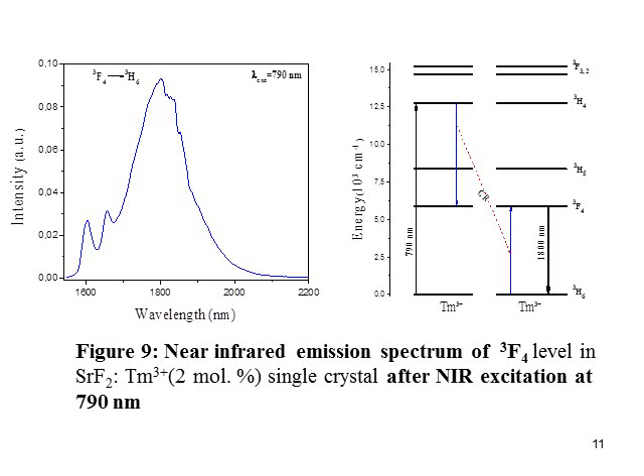We are also able to record the infrared emission around 1.8 micrometer, which is known to have many practical uses. The emission is reinforced by a phenomenon of cross-relaxation very effective in view of its intensity.